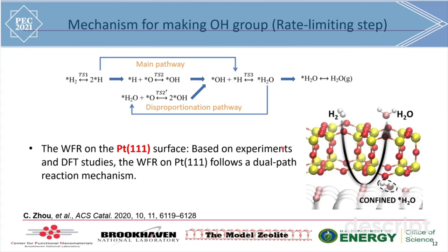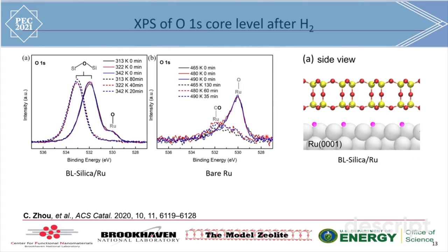And in our experiment, we want to combine the DFT calculation with experiments to further support this reaction mechanism, and we also want to characterize the confinement effect by conducting this reaction in a system with a silica bilayer on top. The main technique we use is ambient pressure XPS. So in our experiment, we followed the oxygen 1s core level during the reaction.